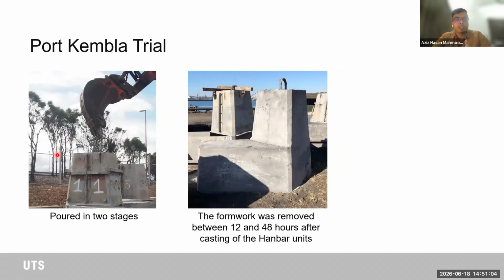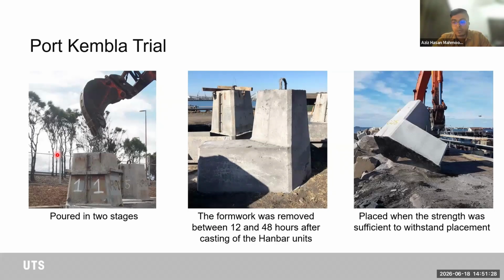Now, I should give you a reminder that in 2018, these were cast in June and July. So the average temperature ranged from 3 to 10 degrees Celsius. So it's very cold and not an optimal environmental condition for any concrete to reach that level of strength in ambient curing conditions. So when we achieved sufficient strength, these units were placed.